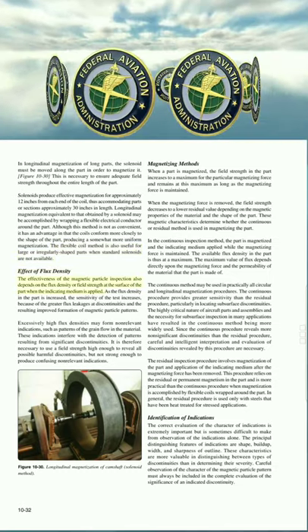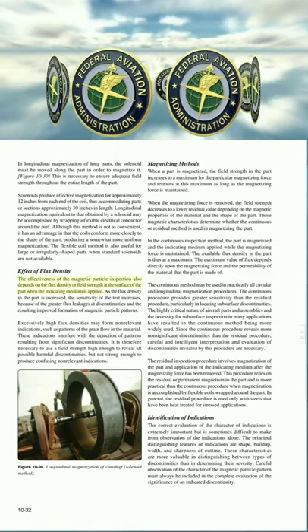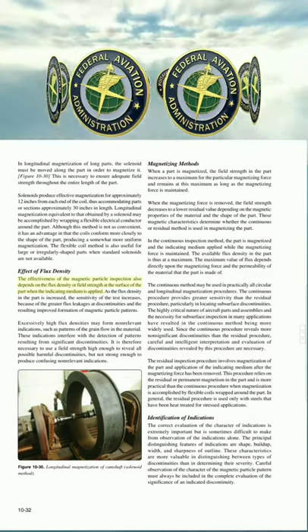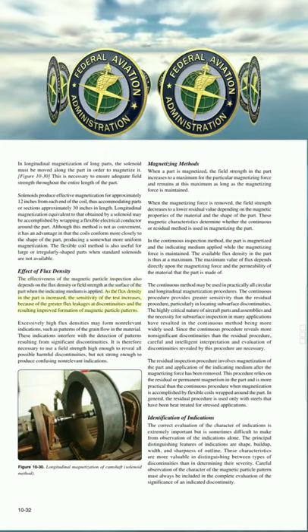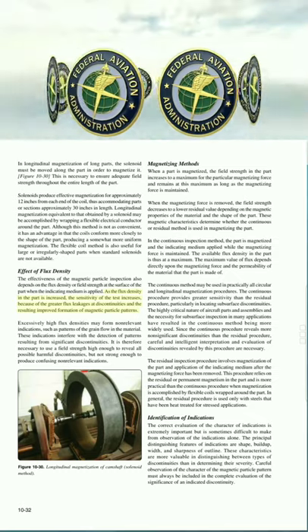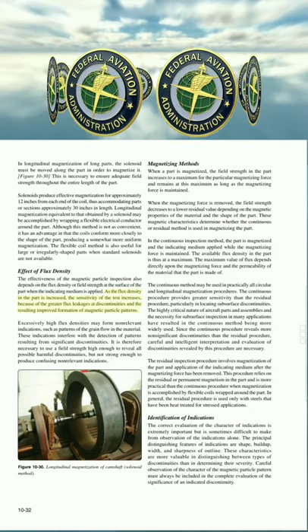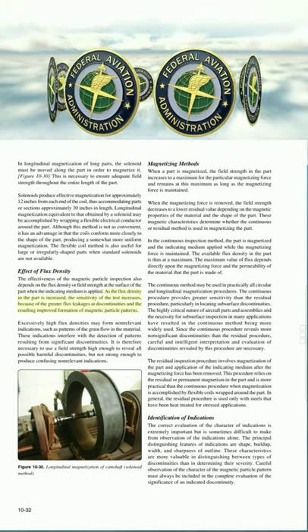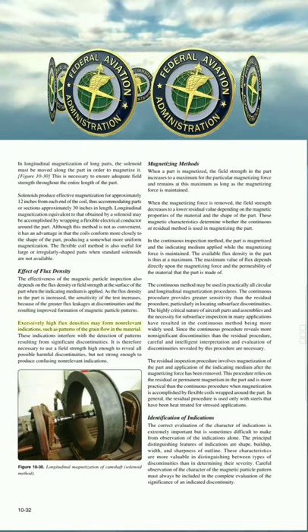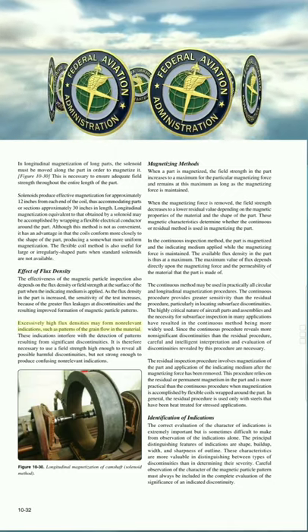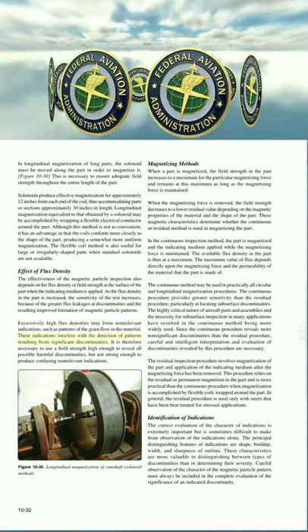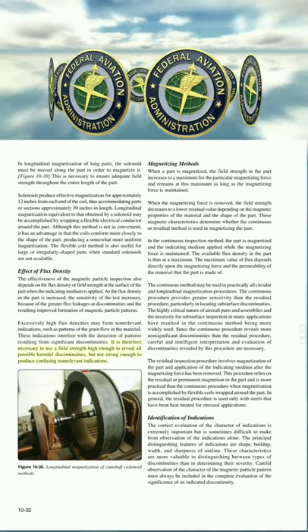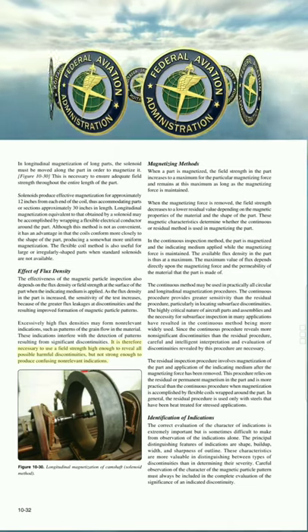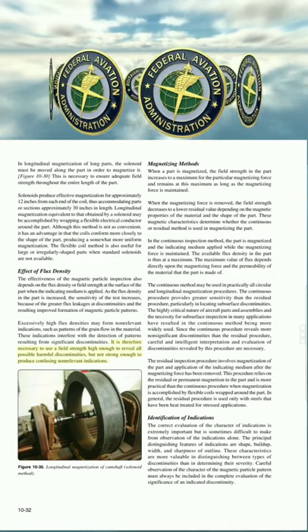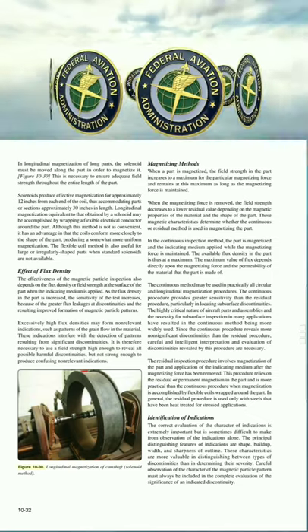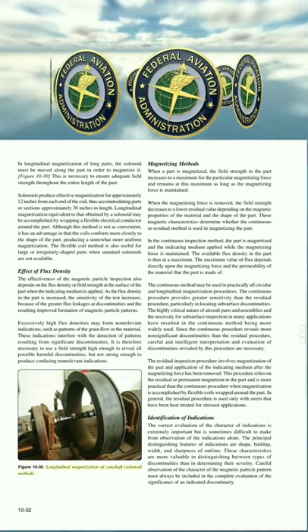Effect of flux density. The effectiveness of the magnetic particle inspection also depends on the flux density or field strength at the surface of the part, when the indicating medium is applied. As the flux density in the part is increased, the sensitivity of the test increases. Because of the greater flux leakages at discontinuities, and the resulting improved formation of magnetic particle patterns, excessively high flux densities may form non-relevant indications, such as patterns of the grain flow in the material. These indications interfere with the detection of patterns resulting from significant discontinuities. It is therefore necessary to use a field strength high enough to reveal all possible harmful discontinuities, but not strong enough to produce confusing non-relevant indications. Figure 10-30. Longitudinal magnetization of camshaft, solenoid method.